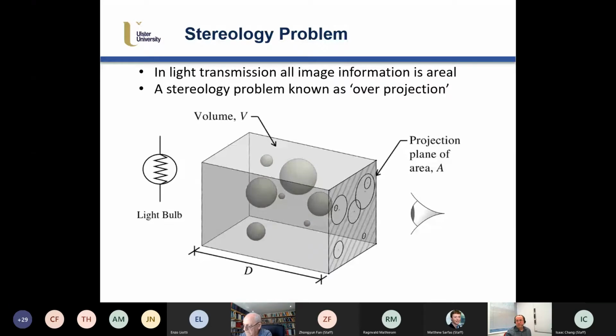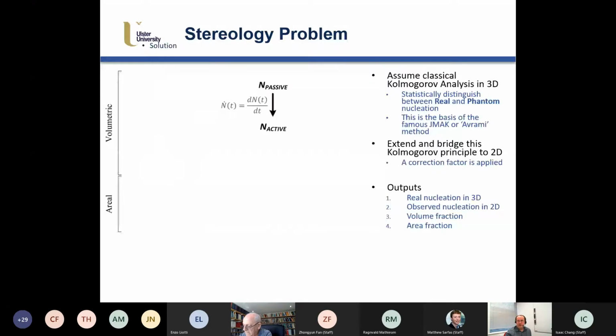So trying to get to the bottom of this and trying to tackle this problem, we returned back to the Kolmogorov definitions of the Avrami equation. So one of the most famous equations in transformation kinetics. If you go back to Kolmogorov, he was a statistician, and he did a lot of statistical analysis and introduced this concept of real and phantom nucleation. And so we revisited, and what we looked at is you have this nuclear activation rate, first of all.